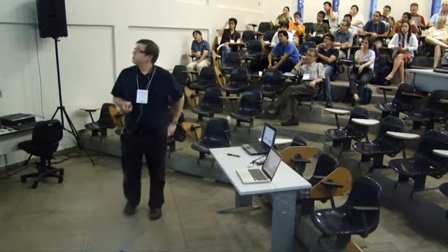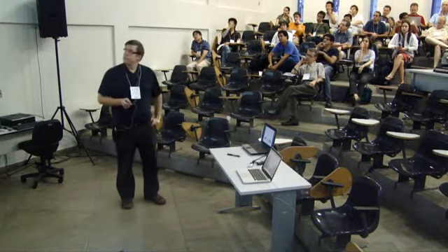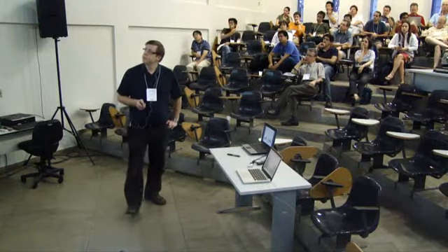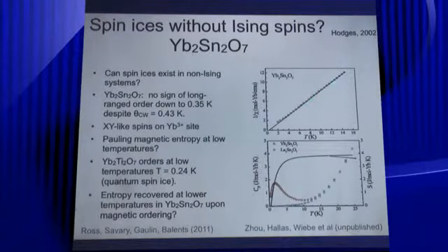Okay, what about spin ices without Ising spins? How strict is that constraint? This is looking at data on ytterbium stannate. We heard a lot of information this week in talks, nice talks on ytterbium titanate. Ytterbium stannate, again, has very similar susceptibility to ytterbium titanate, so it has no long-range order down to 0.35 Kelvin. The Curie-Weiss constant is slightly higher, so a little more ferromagnetic at 0.43.